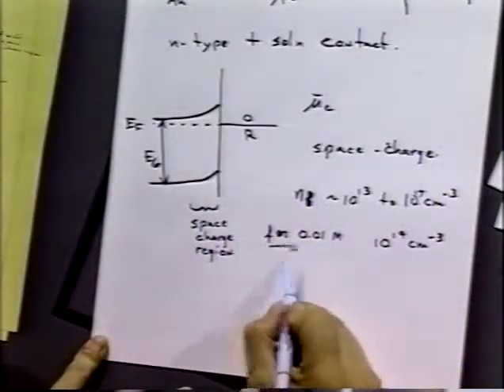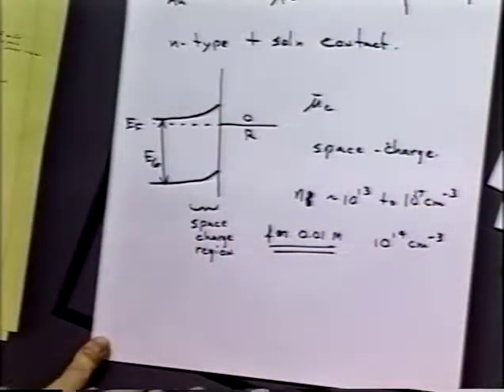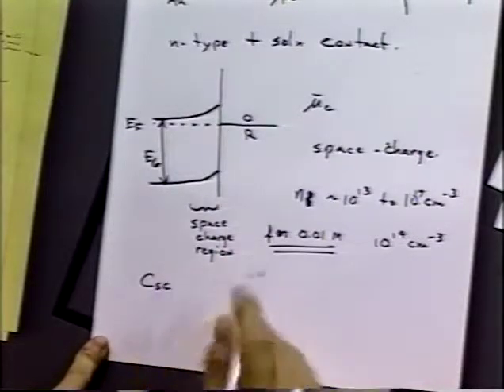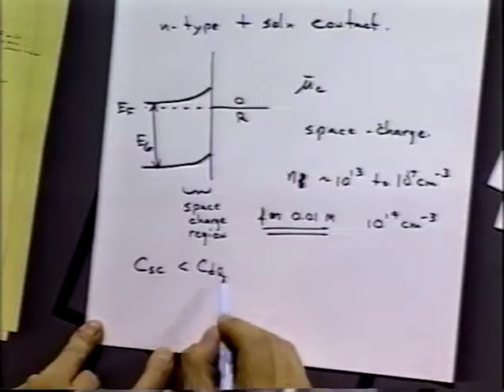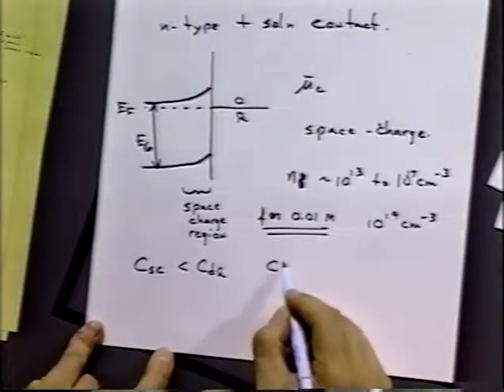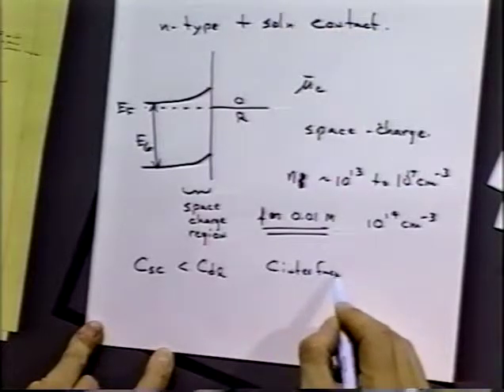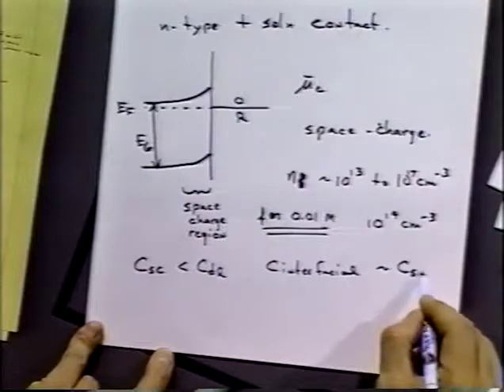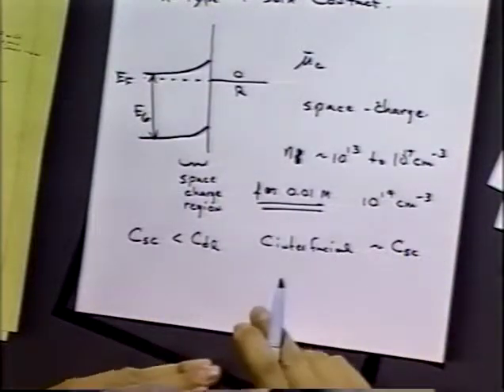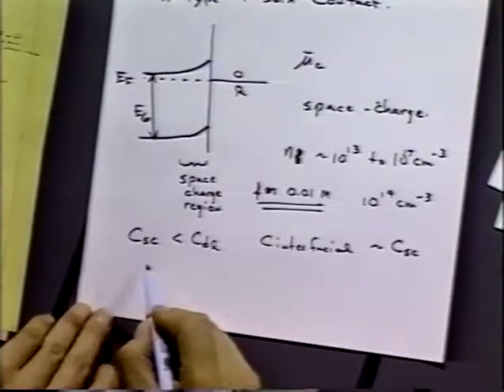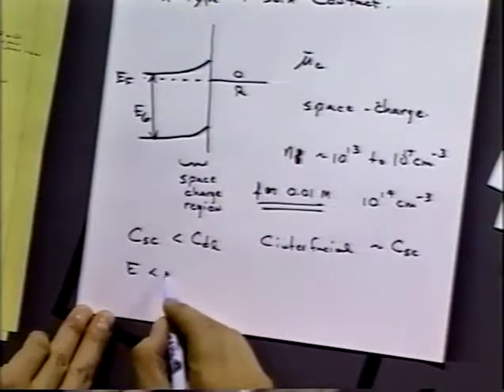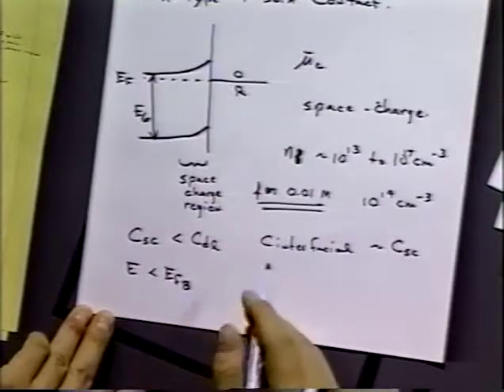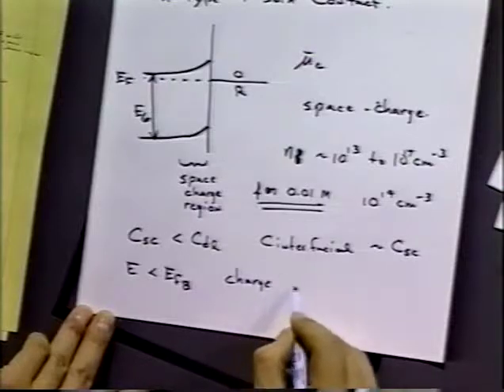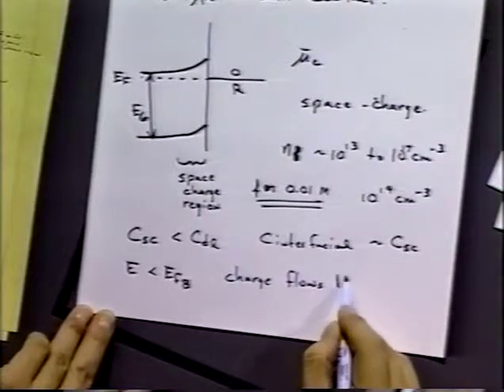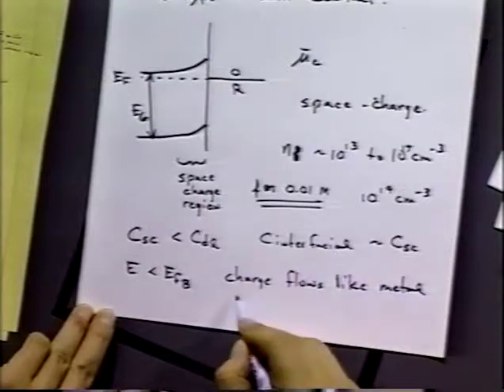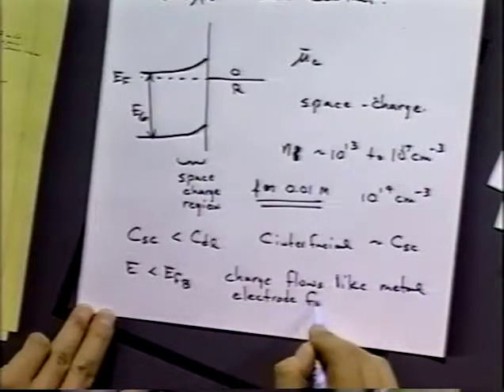Now, because there are typically fewer charge carriers than in the electrolyte, it turns out that the capacitance of the semiconductor is usually less than the capacitance of the double layer in the electrolyte. So the interfacial capacitance is always dominated by the lower capacitance component, and that's going to be approximately the capacitance of the space charge region on the semiconductor. And just to reiterate, when E is less than E flat band, the charge flows like metal electrodes. N-type systems.